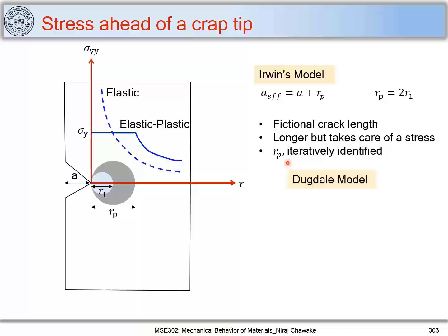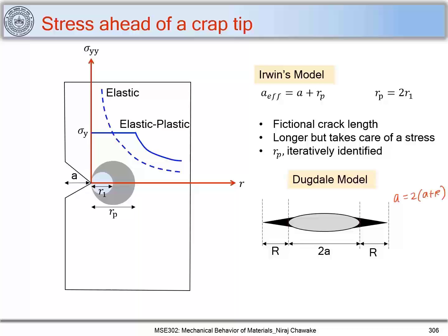Now based on this, Dugdale has proposed a model which is very useful. In that model, he considered a crack length of 2a and plastic zones of length R on both sides. So you have an effective crack length. Let me write that down. So the effective crack length here can be written as 2 times a plus R.